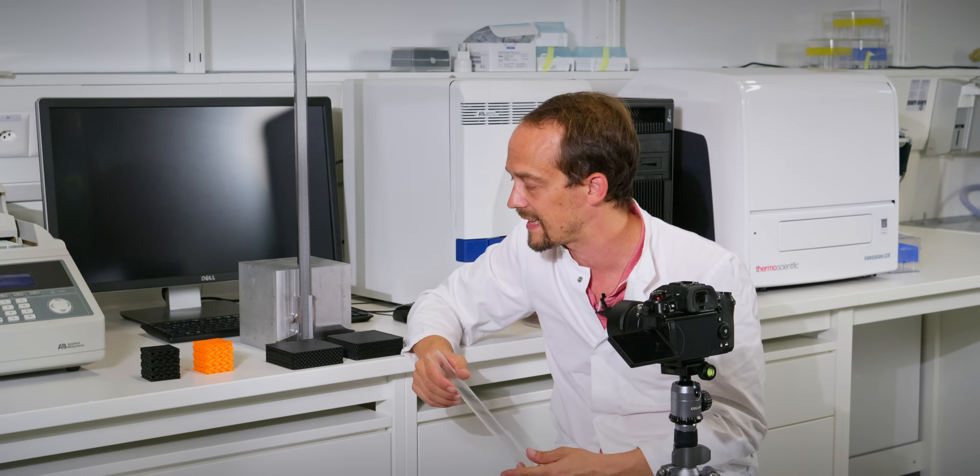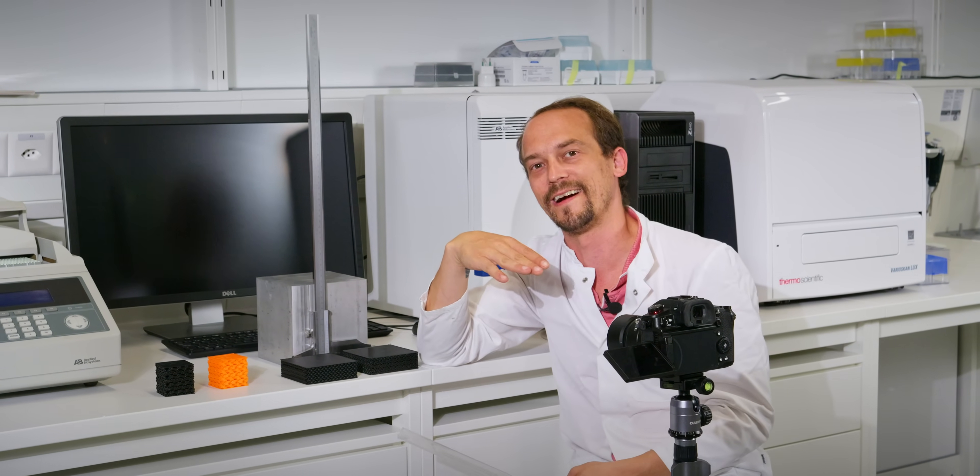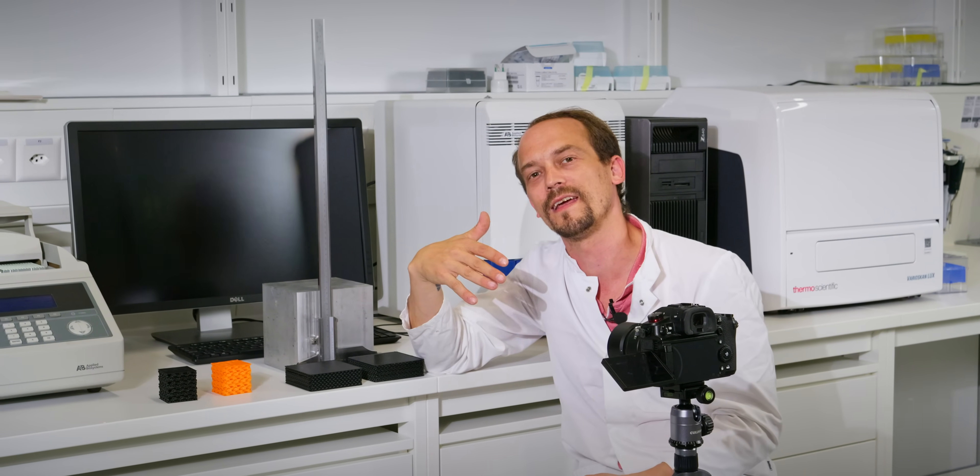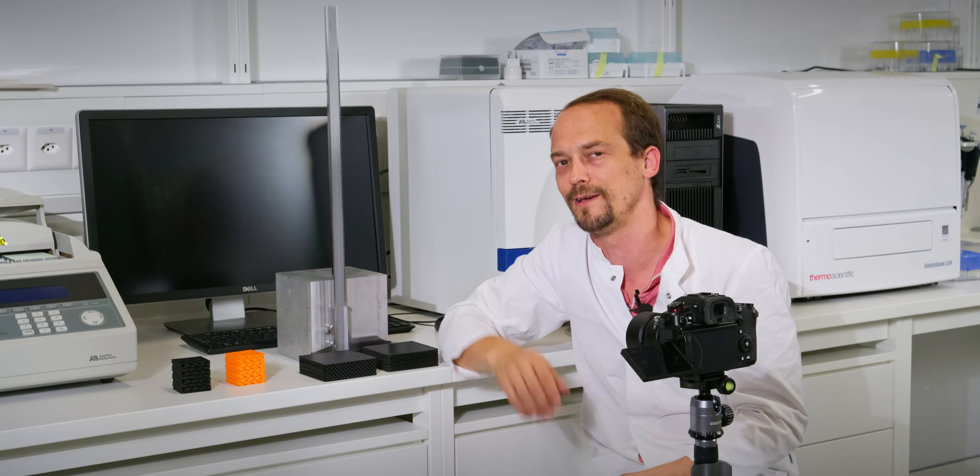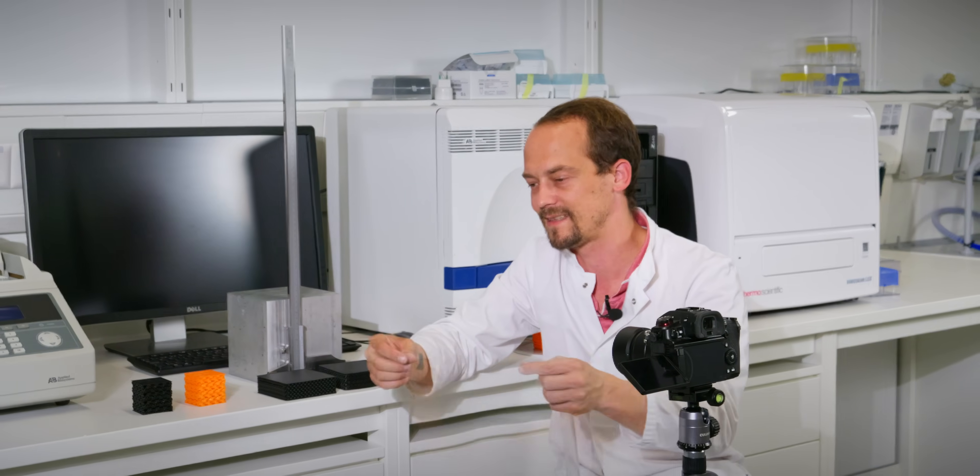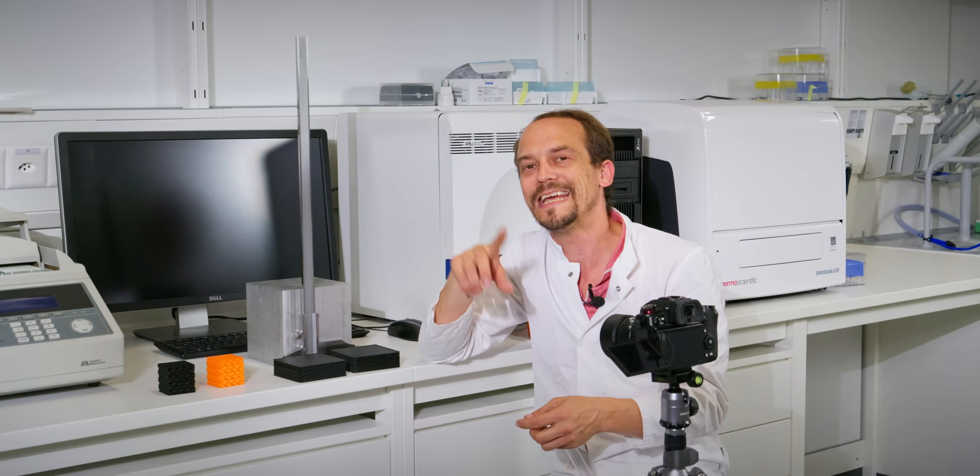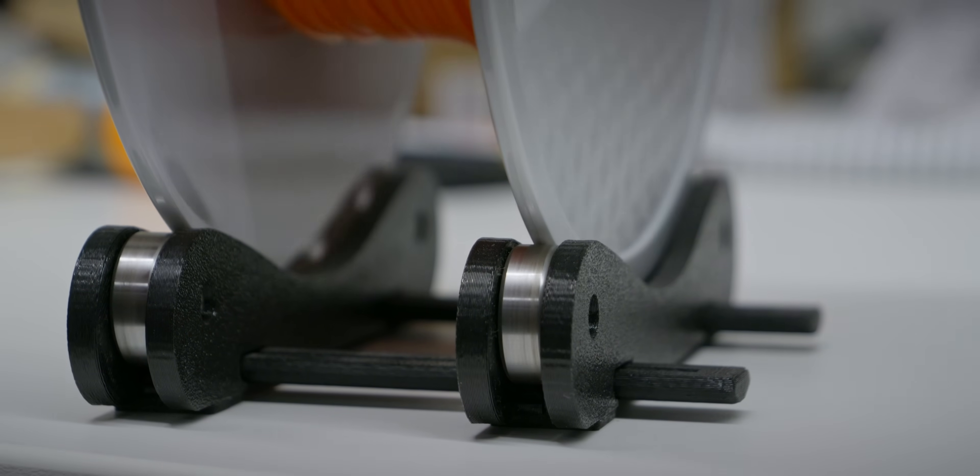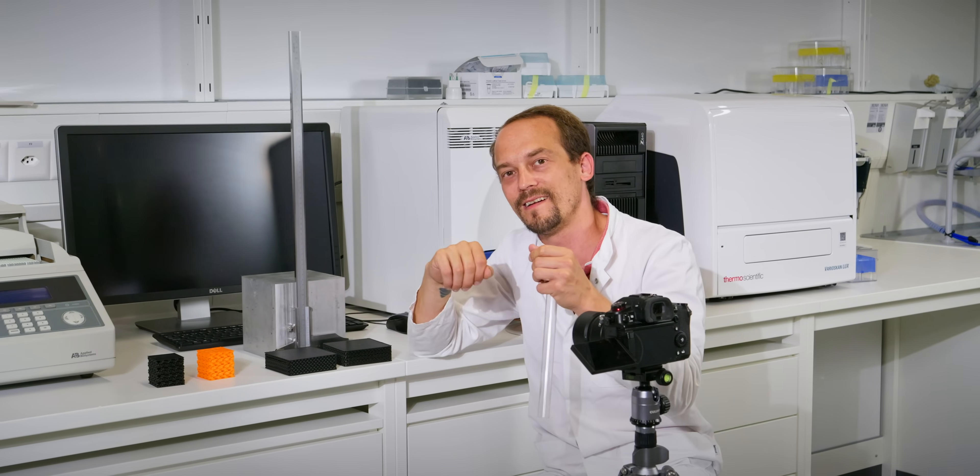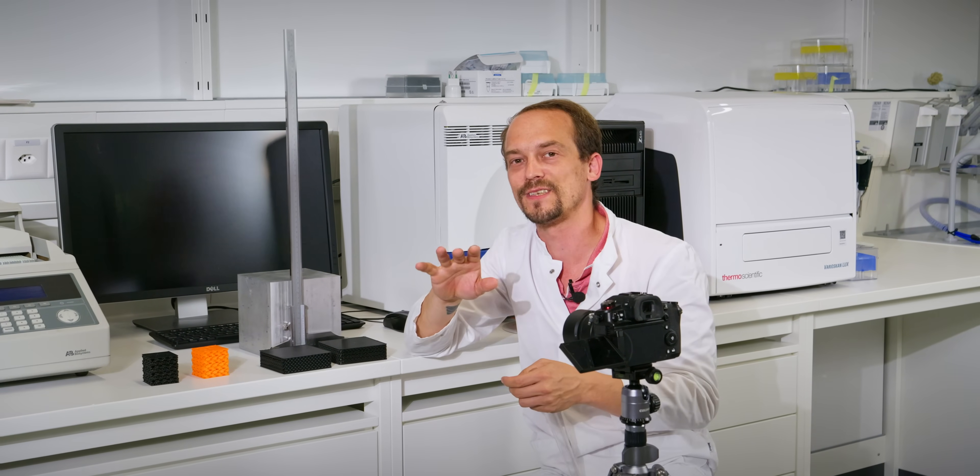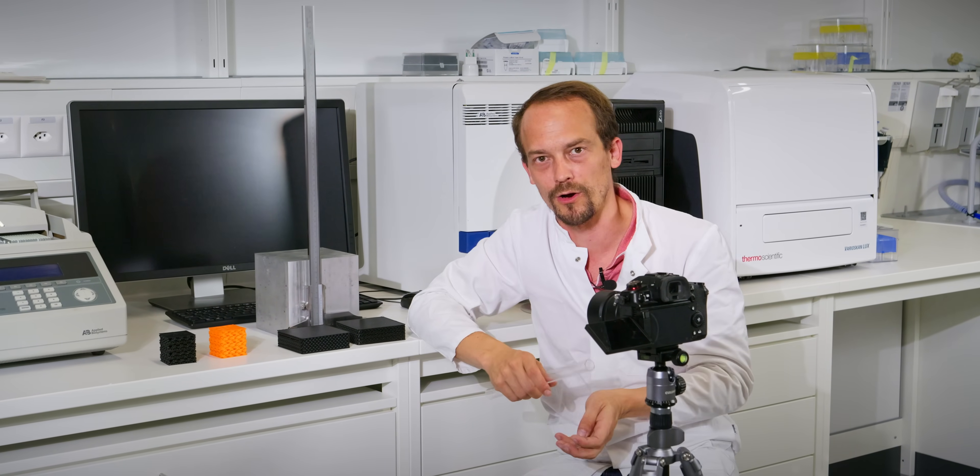And I was bummed out because I thought there were PEBAs before. They printed super bad. So I thought another company like that. But then I actually read through their how to use guide again. And I normally don't really read manuals. In this case, I should have. So I set the spool on an easy roll. So basically, I had ball bearings below. So it really easily spins because otherwise it already pulls the string a little thinner on your extruder and pulls it out. And as soon as I did that, all the problems were gone.